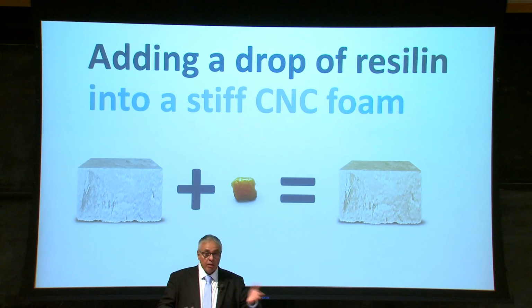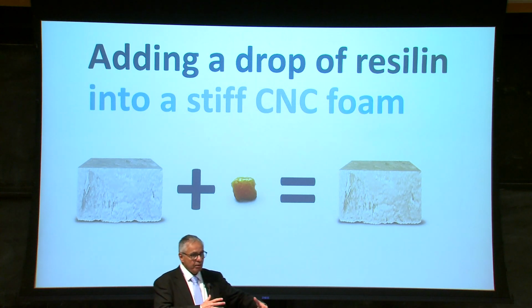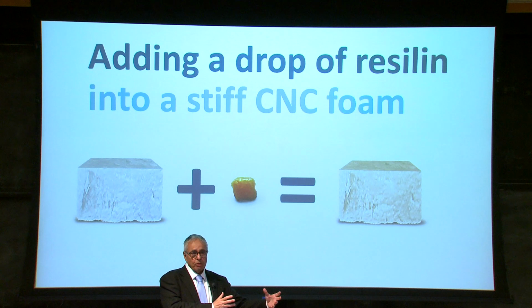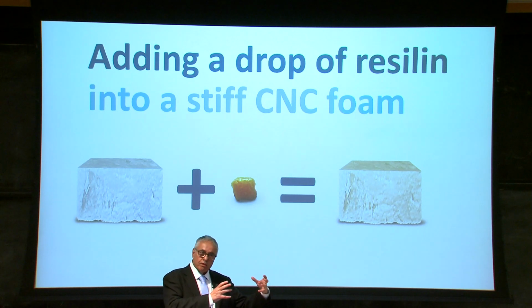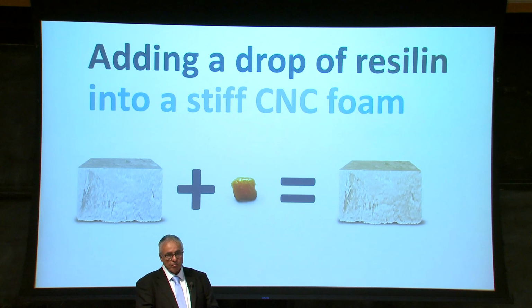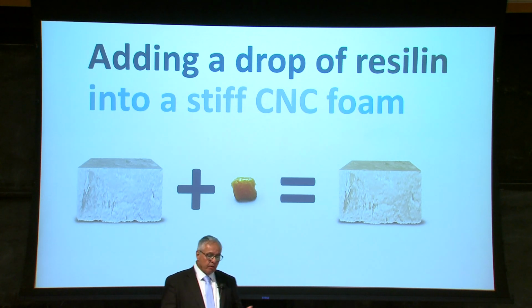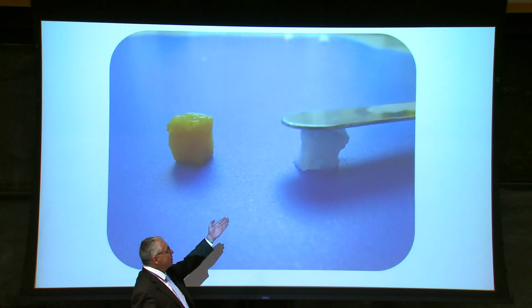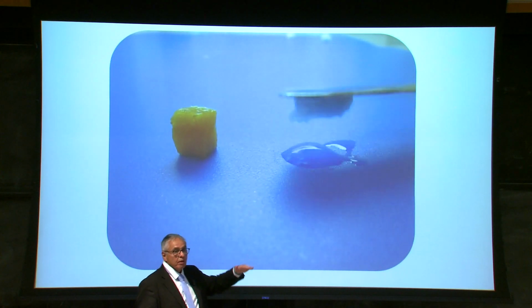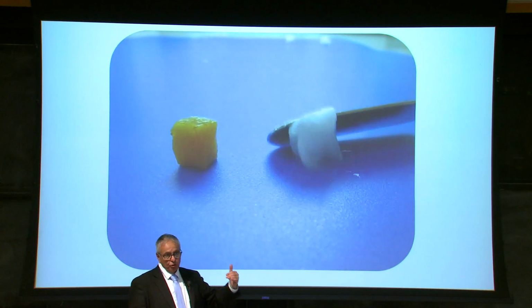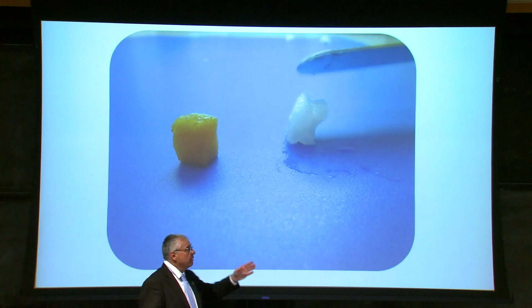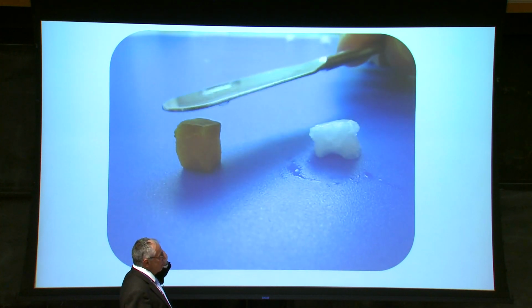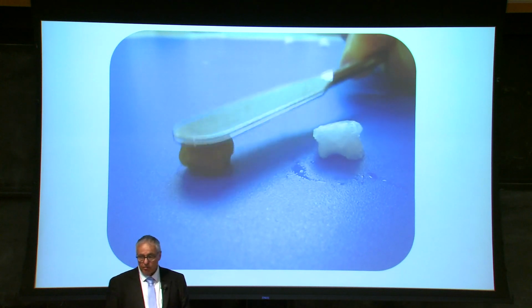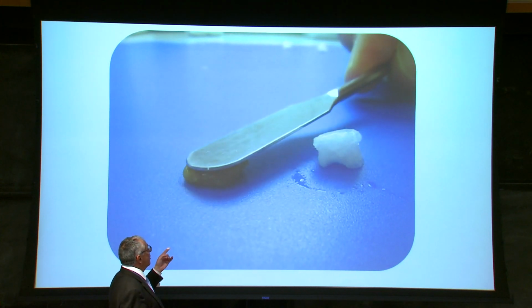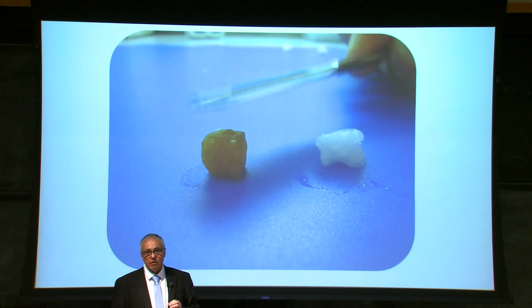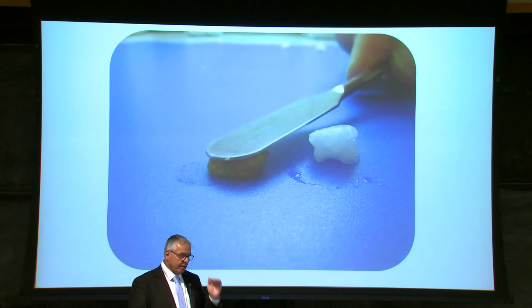So the guys in the lab said, hey, we have cellulose nanocrystals, which are really tough, really nice material. We can make foams. What will happen if we take this foam and add a little bit of CBD resilin? So you can see a short video here. On the right-hand side, it's cellulose nanocrystal foam in water. I squish it with a spatula, and you can see it has only plastic deformation. So not so exciting. On the left-hand side, it's actually the same thing, except that we have now some resilin. And sure enough, you can see very, very different mechanical properties. So you can do it again and again and again.